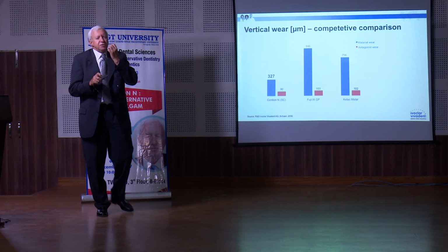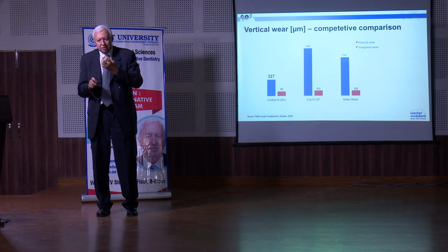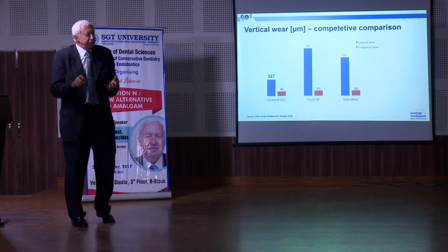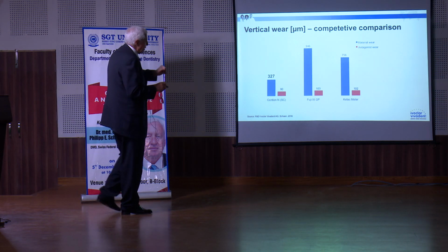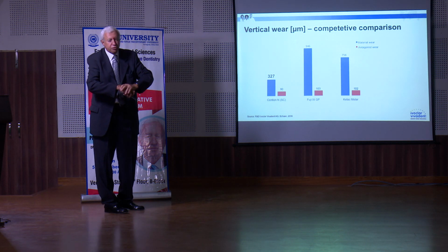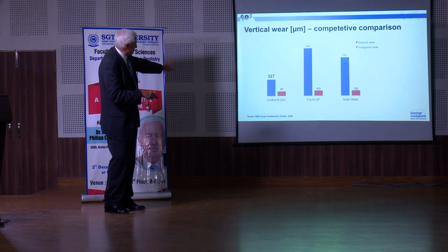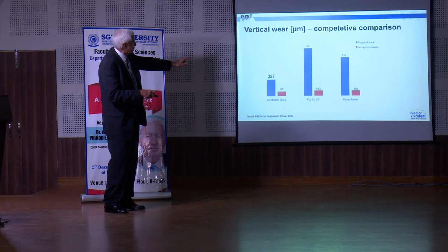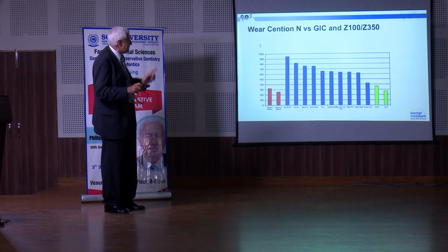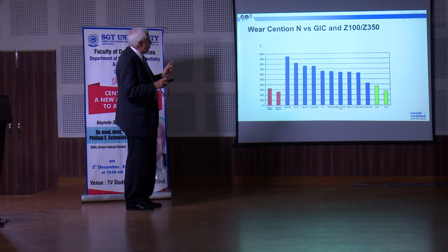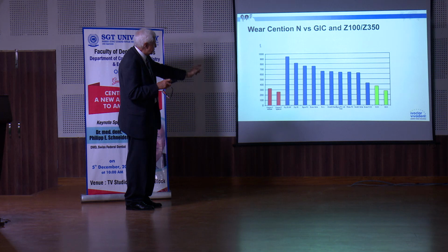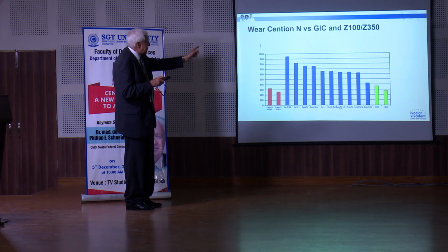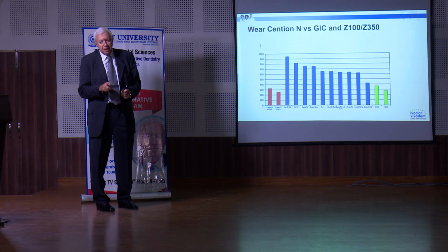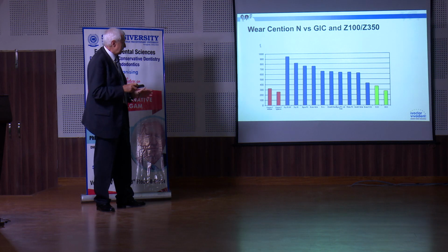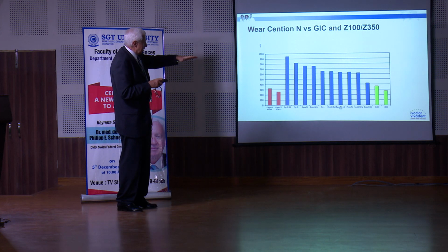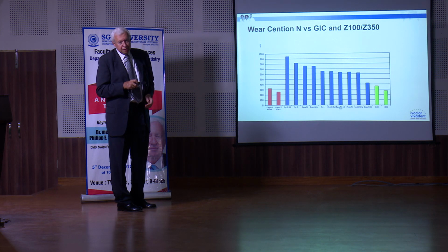You see where it is loss of substance for us, like a car tire. You lose some material. And you see, red is ceramic, the antagonist. Because it is ceramic, it is very hard, it's very strong. But you see, we have some loss of substance with Cention N, it's okay, but not so much like glass ionomer cements. And we checked also the wear of Cention N versus glass ionomer cement. Glass ionomer cement is blue, red is Cention N, and green is Z100, Z350 from 3M, a composite material. So you see, Cention N is really lying in the range of a composite material.